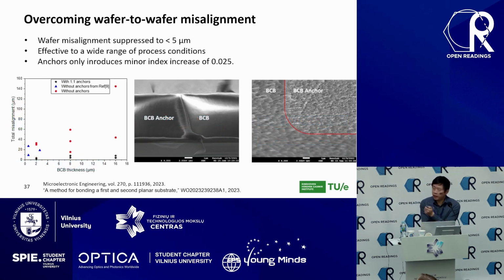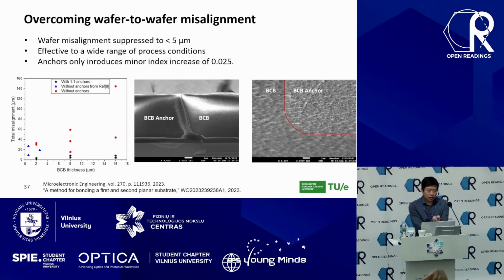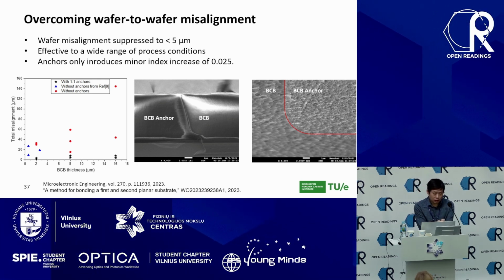And the benefit is enormous, as you can see. When we bond without anchors, we typically get tens of micrometers misalignment, or even more than 100 micrometer. And then you see the black dots, which is with our anchor system, we can press it down to just a few micrometers.